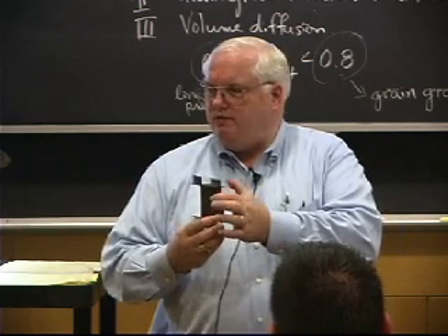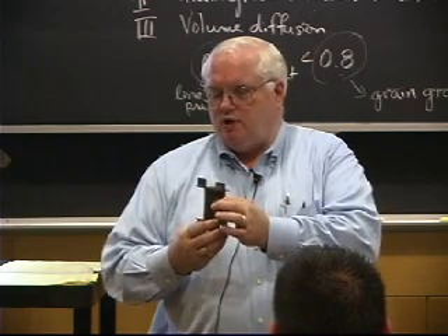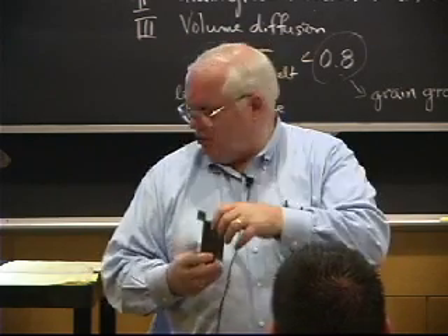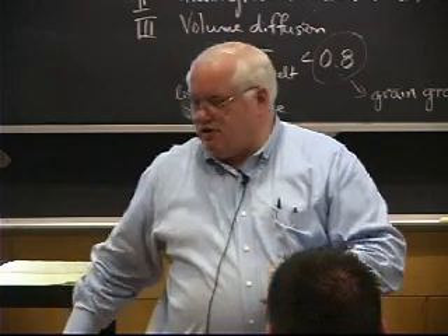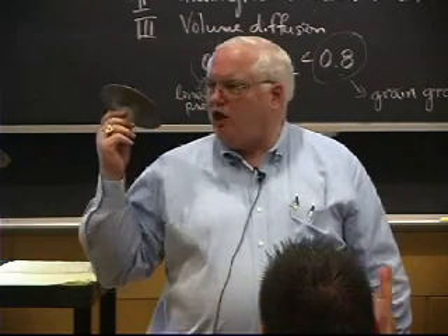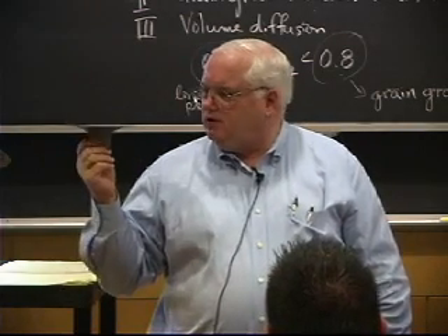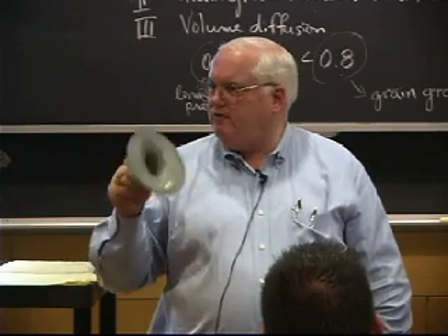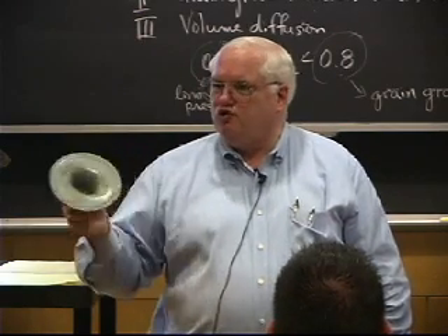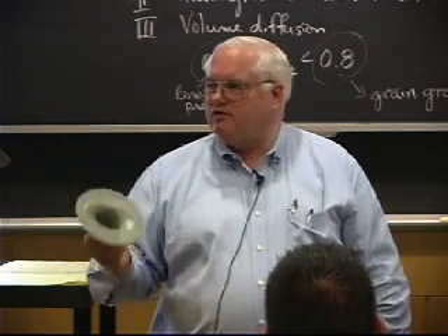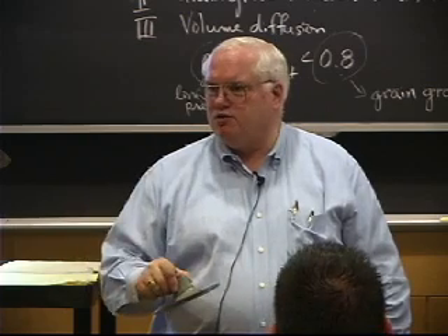So you get creep if you have grain boundaries. The metal will deform readily, and it turns out what you do in superplastic forming is you make lots of grain boundaries, and you get it to the point where the creep occurs at very, very low temperatures, so that you can form it by a creep process rather than just mechanical deformation.